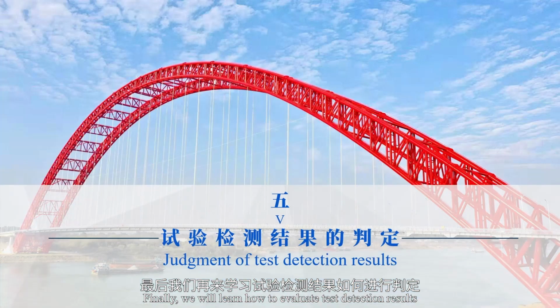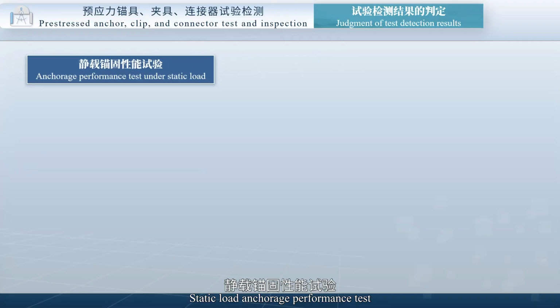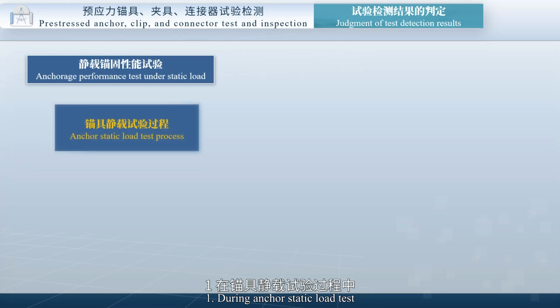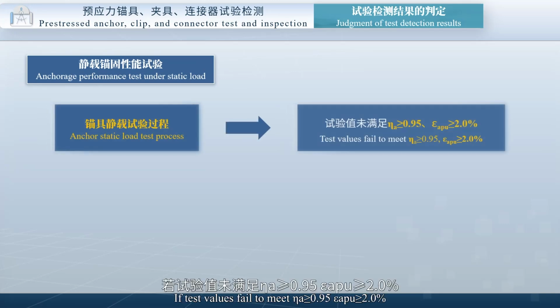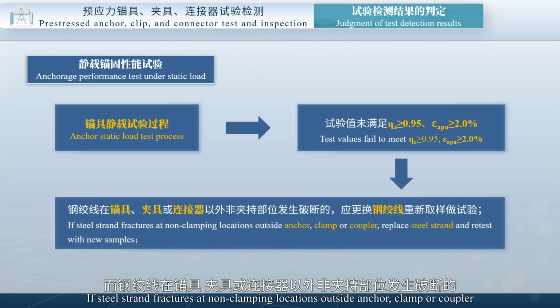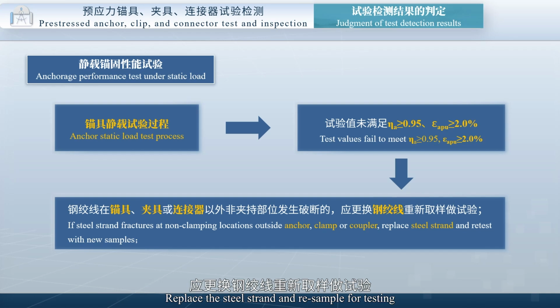Finally, we will learn how to evaluate test detection results. Static load anchorage performance test. First, during the anchor static load test, if test values fail to meet eta A greater than or equal to 0.95 and epsilon APU greater than or equal to 2%, and the steel strand fractures at non-clamping locations outside the anchor, clamp, or coupler, replace the steel strand and resample for testing.